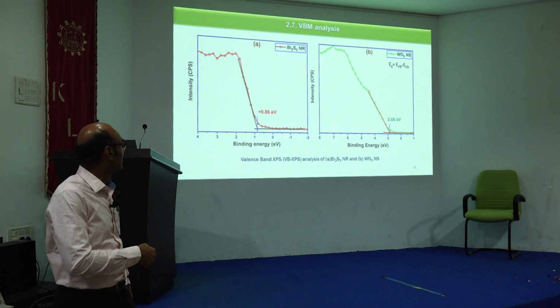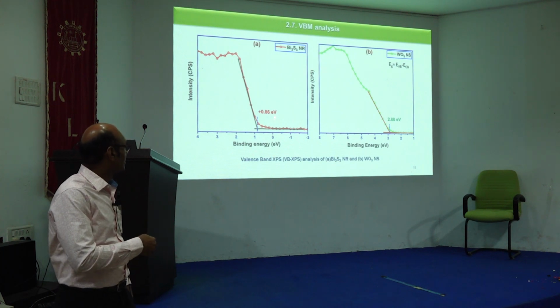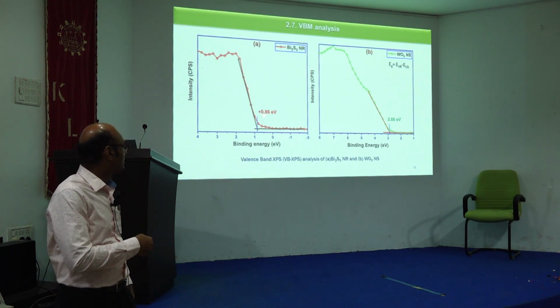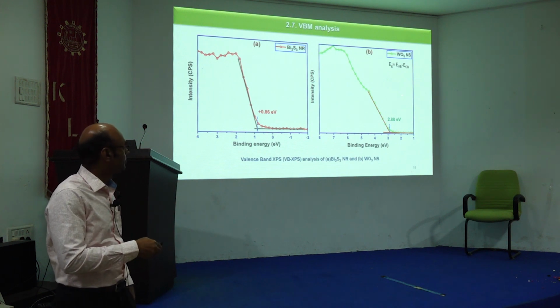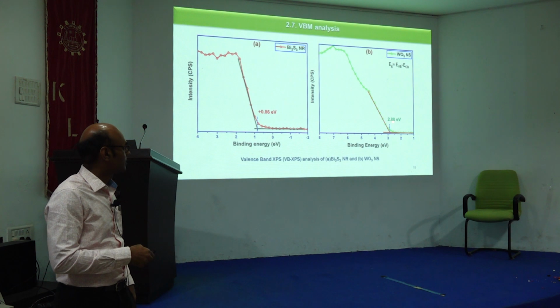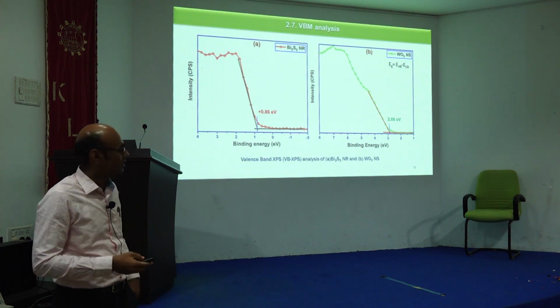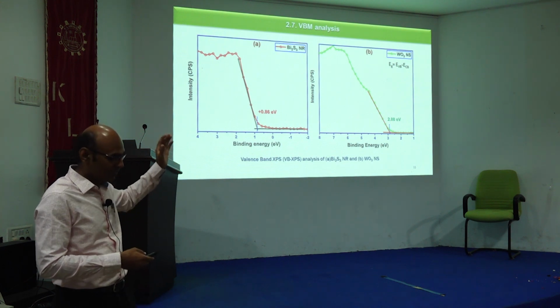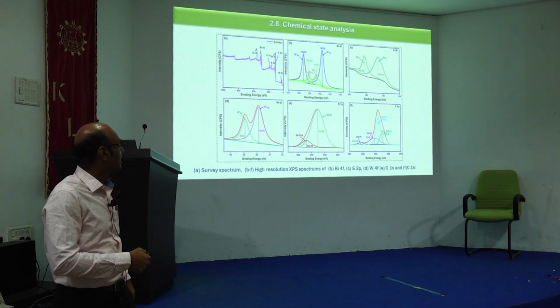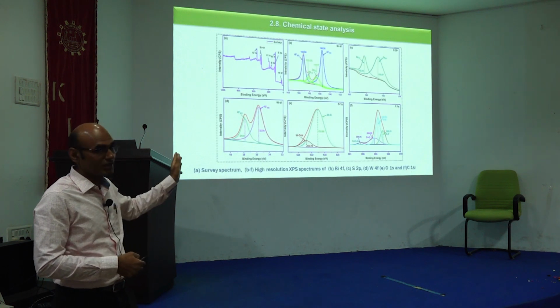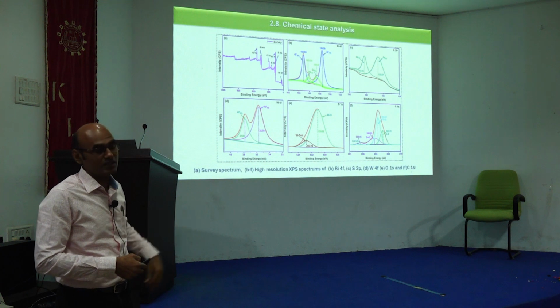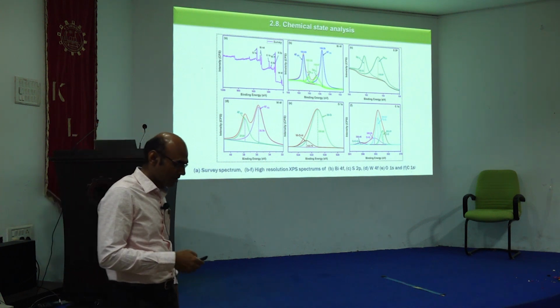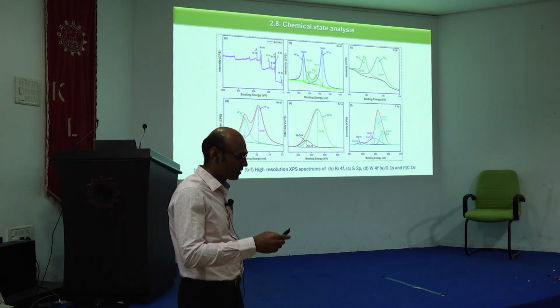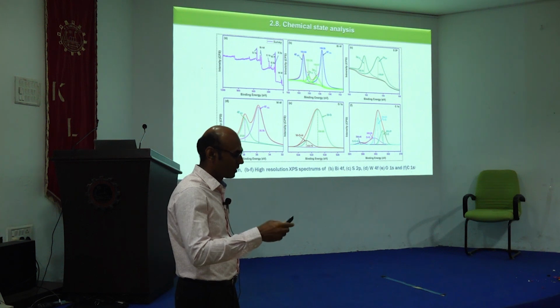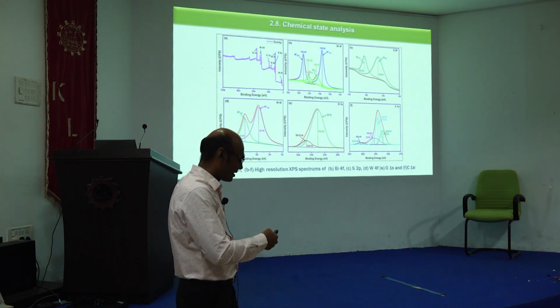We have calculated that the valence band level is 0.86 for bismuth sulfide, and the valence band for tungsten trioxide is 2.88. This way we have calculated the conduction band and the valence band levels as well. So this also gives some more details confirming the presence of bismuth sulfide, tungsten trioxide and carbon nanotubes in terms of chemical composition.